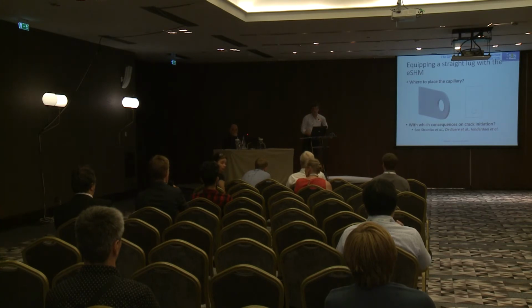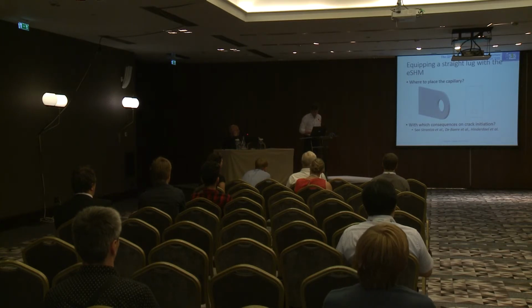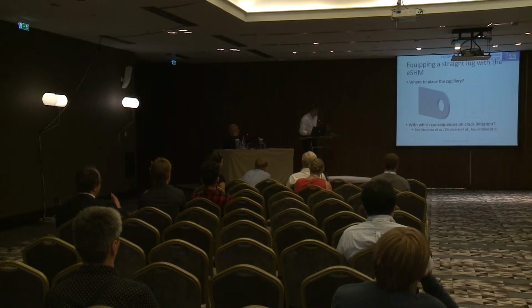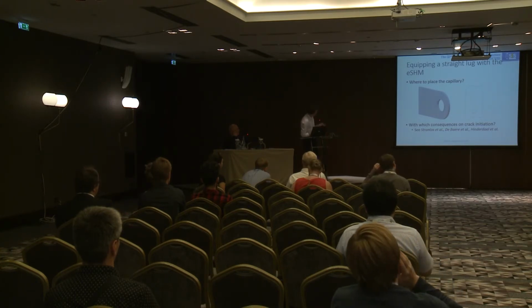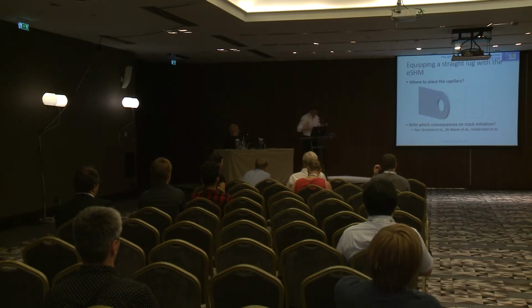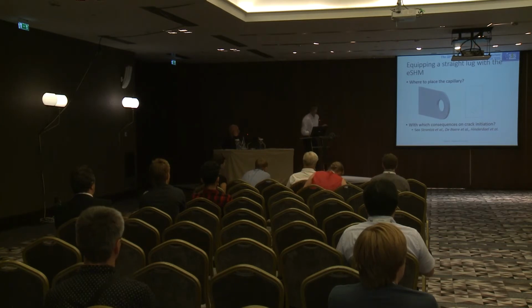Did you measure some kind of stress concentration due to this capillary? Indeed, it's unfortunate, but it's unavoidable to have some kind of stress concentration. It's a question of placing it at the right distance. I don't have the values in my head, but let's say that with the loading you have a maximum tensile axial stress of, I don't know, 250 megapascals at the pinhole connection, and in this region here, without the capillary, you have maybe 200.